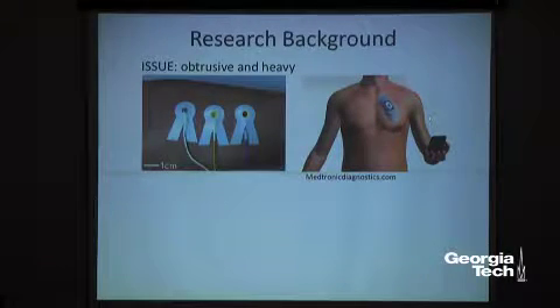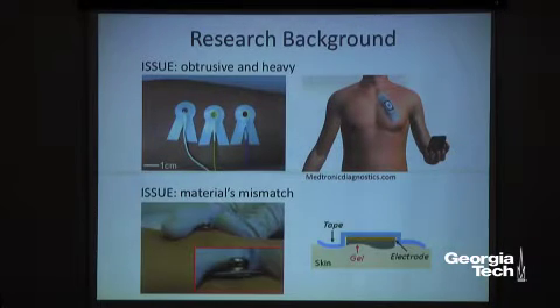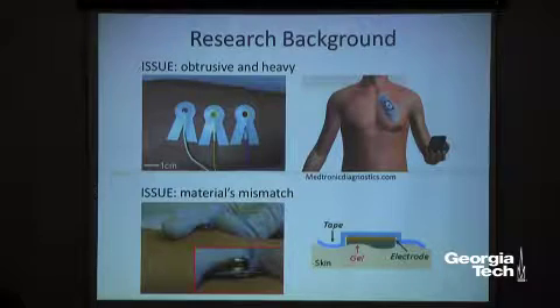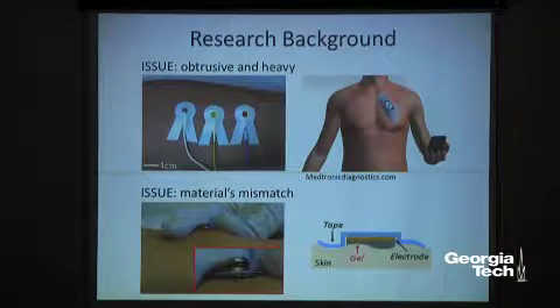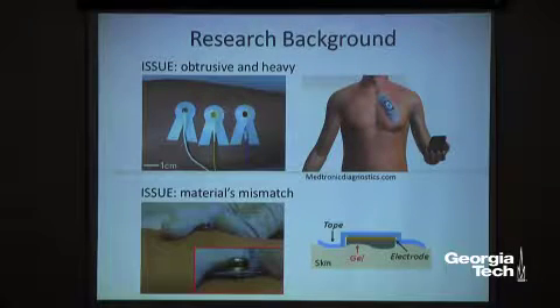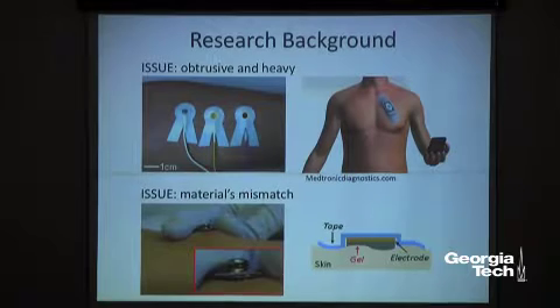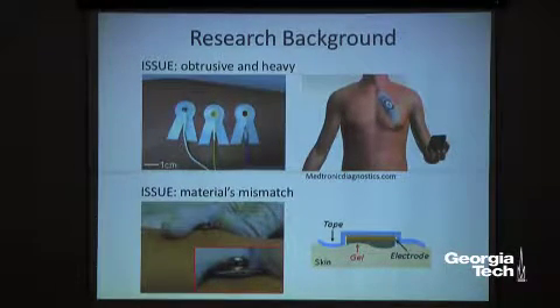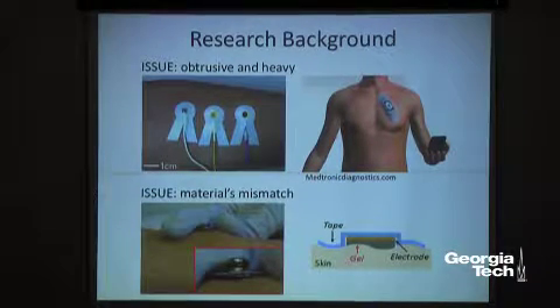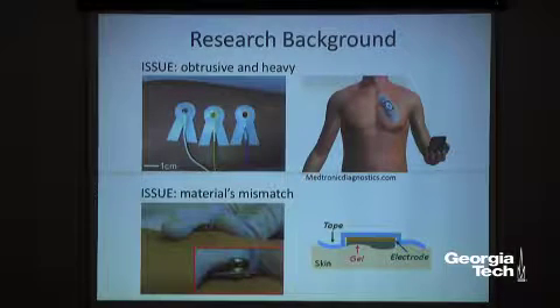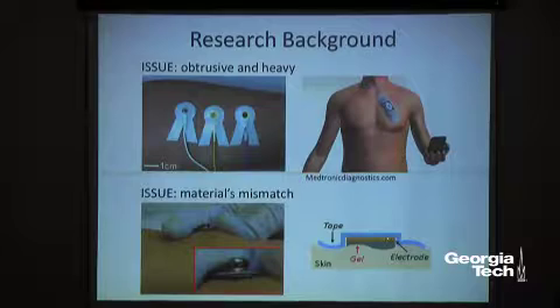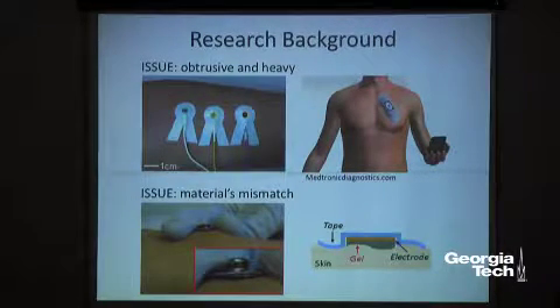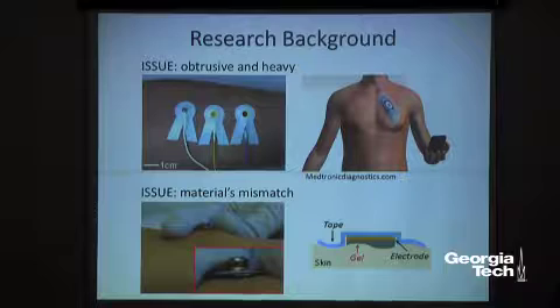So we have to change this material because they still use the same materials. We have a bigger issue once you look at the interface between the device and the skin. Again, this device is mounted on the skin for monitoring electrocardiograms. If you look at your skin, it looks flat, but if you look closely in terms of microscopic view, you have this wavy pattern. So normally we have about hundreds to 500 micrometers in terms of wavelengths and amplitude difference on the skin surface. So as you can imagine, the metal, gold, tin, or silver, they are rigid and flat. So if you put that electrode onto your skin, then you will see an air gap between those two materials, which is bad for signal recording because it can enhance electrical impedance.